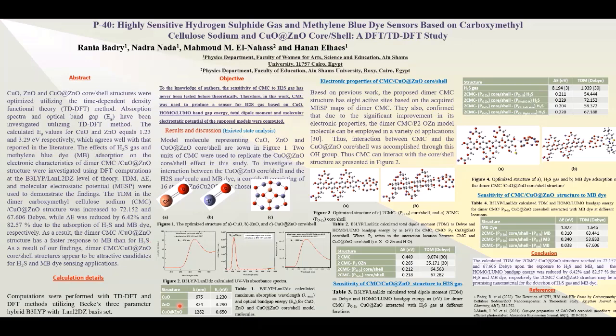Based on our previous work, it is concluded that metal oxides can interact with CMC through the hydroxyl group of CMC. Accordingly, there are two possibilities for the interaction of CMC with the core shell structure. The first interaction mechanism occurs via the hydroxyl group of the CMC and the oxygen atom of the shell. However, the second interaction mechanism proceeds through the metal atom of the core shell structure, as presented in Figure 3.